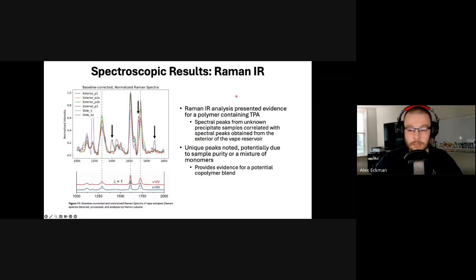The next thing that we did was we actually collaborated with an external collaborator to do Raman IR, and Dr. Vernon was able to find these interesting peak overlaps between what our unknown precipitant was and scrapes of the exterior vape reservoir. So our thought process on this was we would try to see if the spectra from the unknown precipitant matches up with what we know to be the exterior of the tank. And outside of a handful of peaks, these three that are underlined by the arrows, we have a really good match here. And that further kind of pointed us to potentially having some leaching from the reservoir. Now, we still don't know what these peaks are, but it's potentially a contamination is what we think in the sample.